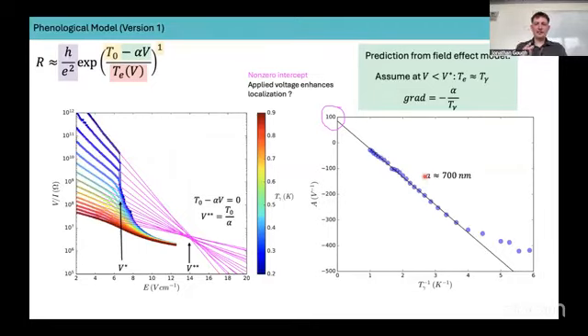It's very interesting that the typical hopping length is very large in this system, 700 nanometers. It typically varies from 200 nanometers to 700 nanometers, depending on the amount of disorder we introduce to the system. For context, in variable range hopping, this typical hopping length has been measured to be 20 to maybe 50 nanometers at low temperatures. So it's much larger than what you would observe in the variable range hopping regime.